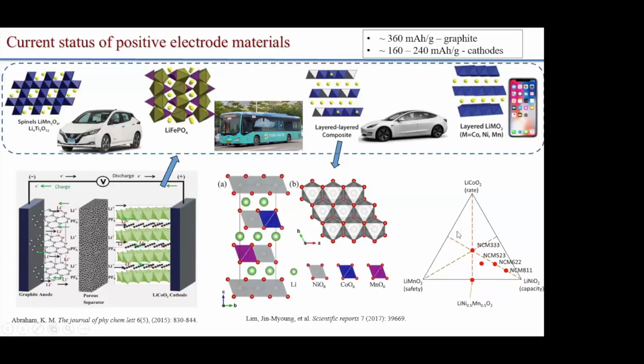So this is the general architecture. And from one device to another, we change the cathode, right? And this is the current status. Graphite's theoretical capacity is about 360 milliampere hours per gram, while cathodes vary from 160 to 240 milliampere hours per gram. And with the right electrolyte, you have an EV or a phone.